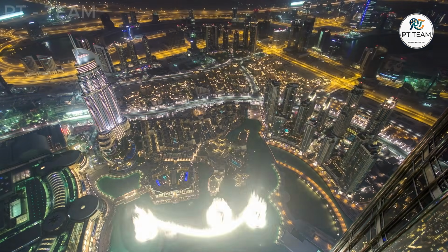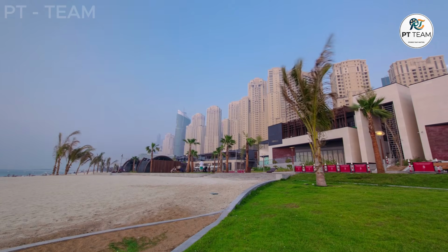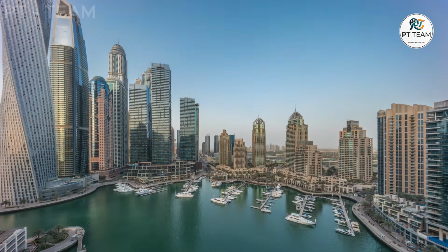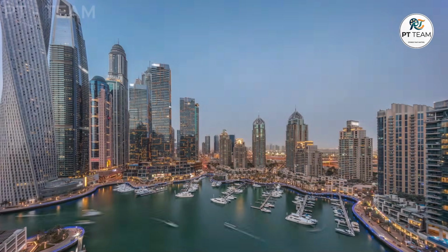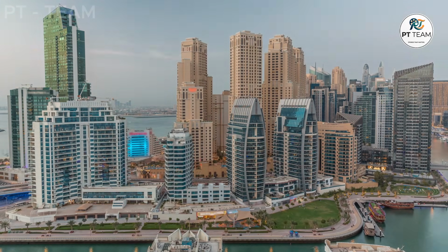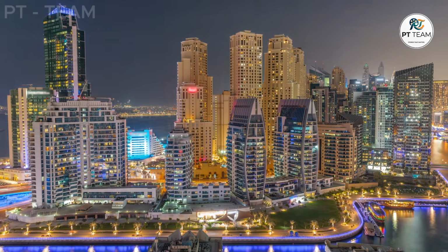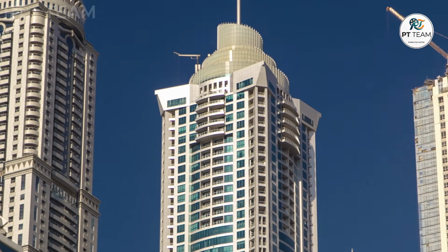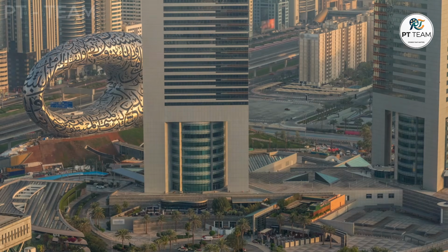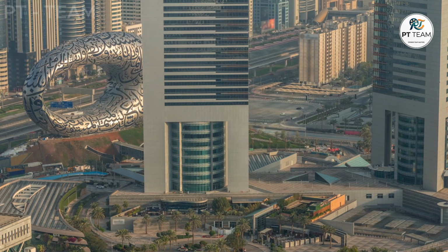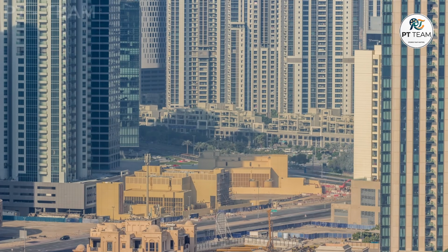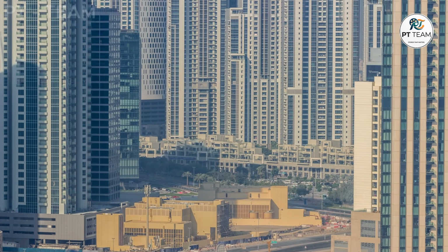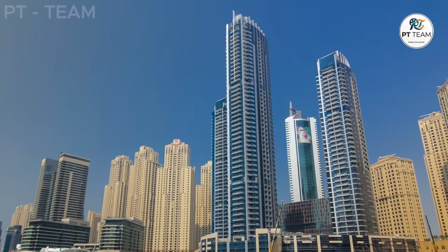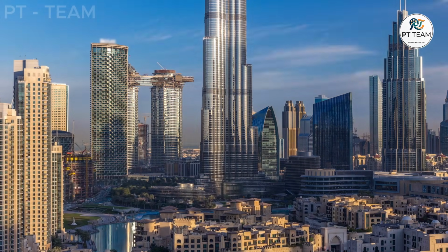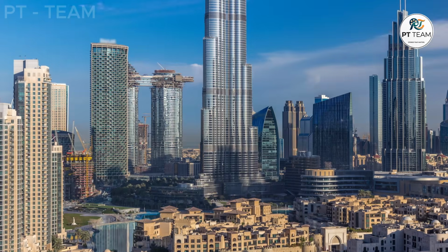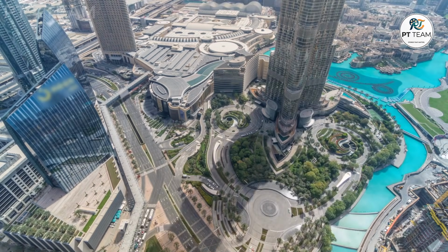The engineers in Dubai are not just fighting a single enemy. They are fighting multiple transport and chemical reaction mechanisms simultaneously, each requiring a completely different defense strategy. We can separate these threats into three distinct categories of destruction. The first mechanism is the chloride-induced corrosion we just explored. Its primary target is always the reinforcing steel, and its ultimate results are internal rust, severe cracking, and the violent spalling of concrete. The second mechanism is known as chemical sulfate attack.